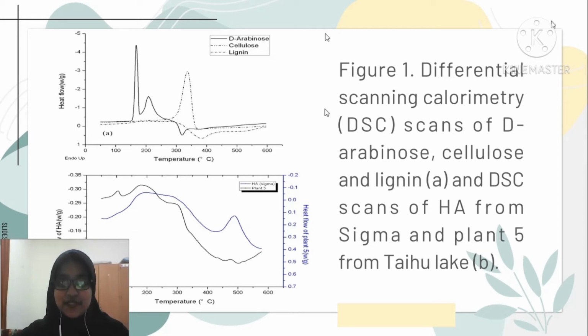Hence, based on the figure, we can conclude that the first endothermic peak appeared between 93 to 110 Celsius. This peak was caused by the melting or glass transition of small molecules. The second endothermic peak, F2, occurred at 175 to 217 Celsius. The first endothermic peak of lignin and the main endothermic peak of monosaccharide occurred at almost the same temperature, which is at 205 Celsius. Therefore, the F2 peaks observed were likely the superposition of several thermal processes and cannot be individually characterized based on the data generated in this experiment.